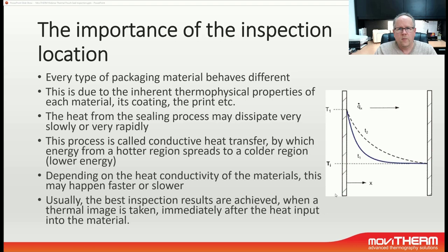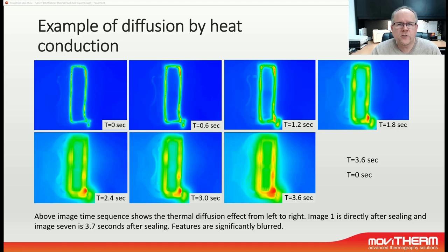So it is very important to understand the heat conduction transfer during a package application, and the best way to determine this is actually by experimental observation. To illustrate this effect better, let's take a look at this time sequence. These are thermal images taken right after a sealing process, with the upper left image starting at T0 and then going up to 0.6 seconds, 1.2, 1.8, 2.4, 3.0, and 3.6 seconds after the sealing process.